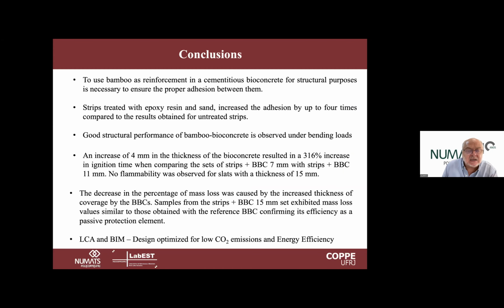So to conclude, just in the last minute, Hector, we see that we need to assure proper adhesion, and that using resin can be a good way to improve that, especially when we put some sand together. Good structural performance with multiple crack formation can be observed. And of course, with 15 millimeters of covering, we protect the material completely against fire.